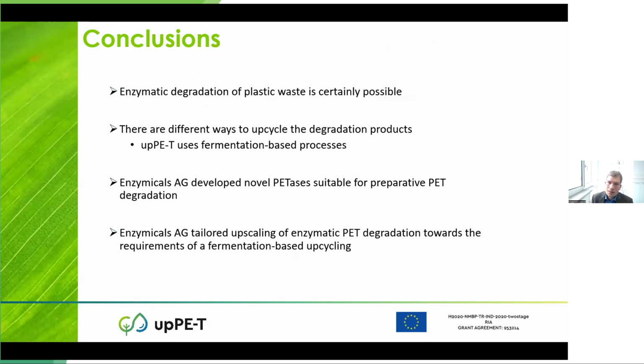And to summarize, we have shown that the enzymatic degradation of PET is certainly possible. And I have also introduced you into the different ways to upcycle the PET degradation products. One way would be the way to enzymatically recycle the PET. And our upPE-T way is to use the degradation process products in a fermentation-based process. I have shown you that Enzymicals develop novel PETases, which we have also used for preparative PET degradation.